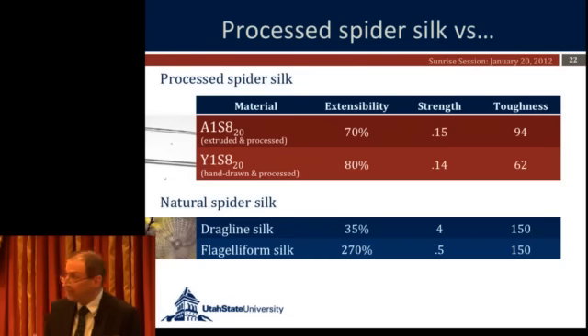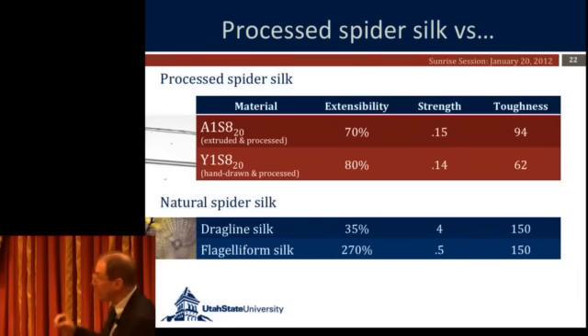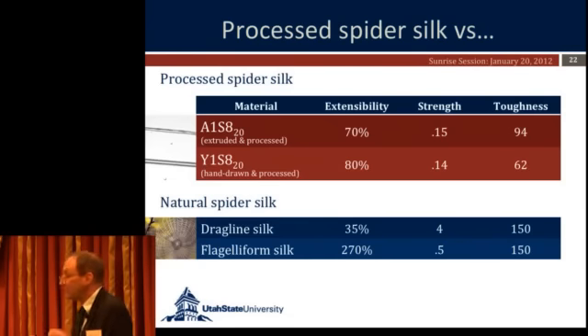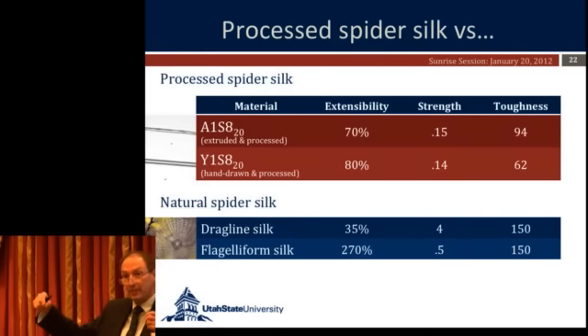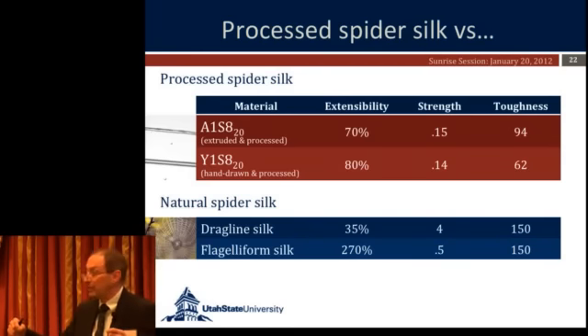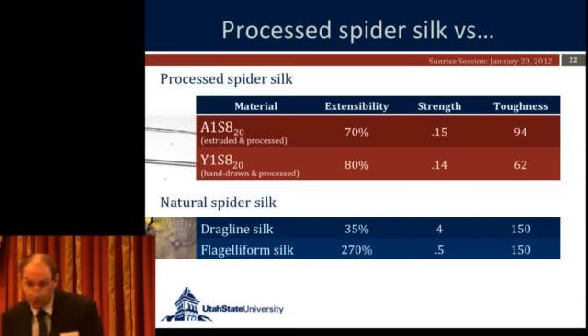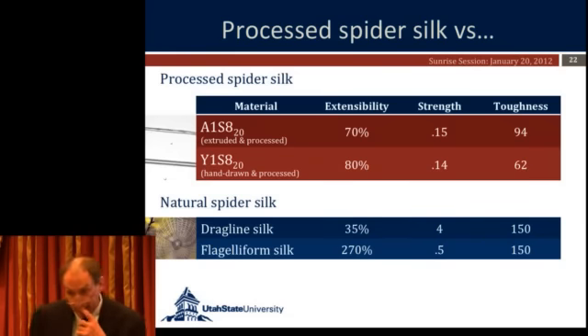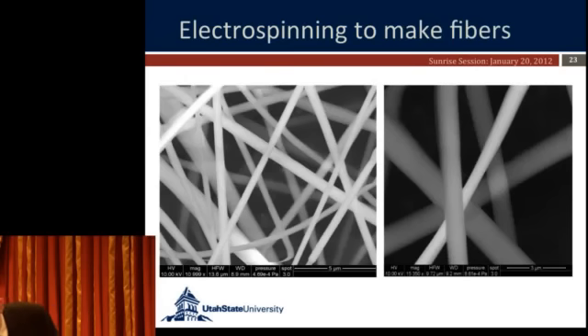The reason that we think this is happening is bacteria only make short proteins. That is, they choke when you make a protein that's very large. So we know that the proteins in the natural silks are very large, and we're making ones that are about 1/5 to 1/3 that size. We think that's the reason why we can't get the strength up. And then I'll show you some data to confirm that in a second.